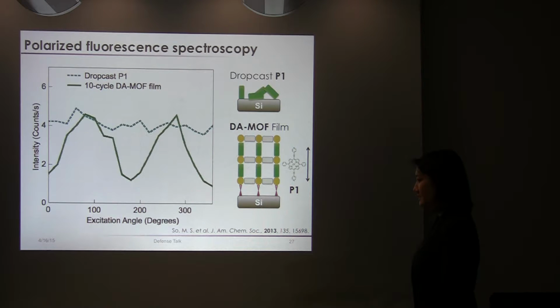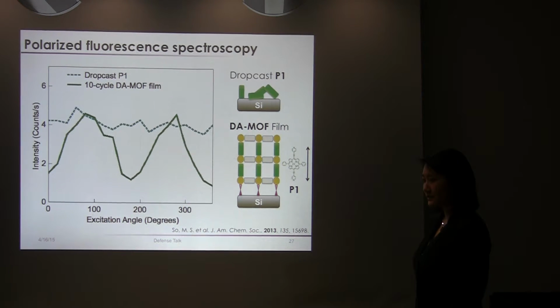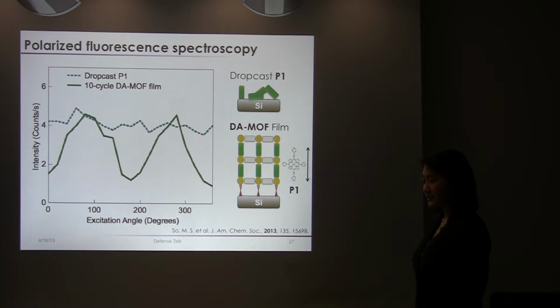Right. What about, maybe you're going to tell us about this, but you did some PXRD or similar experiments, and my recollection is that you don't immediately see order, and maybe not just because of signal to noise, but it takes a while to get. Right. For very thin films, there is very minimal crystallinity, but it's there. I think we need to increase the number of cycles I deposit. So the thicker you make them, the more crystalline they become. Right.